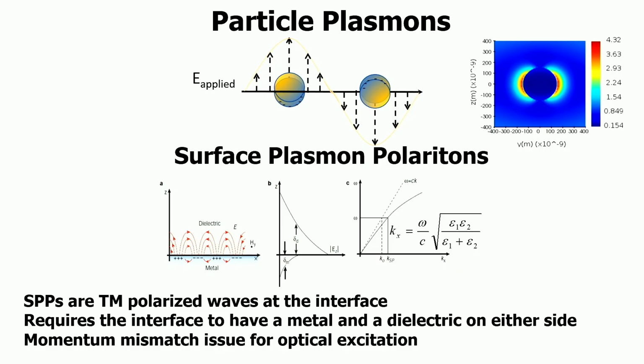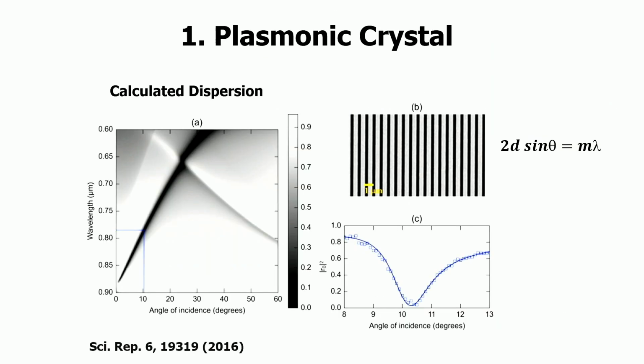To overcome this challenge, people started designing or structuring the metal or the dielectric. The simplest structure is a plasmonic crystal. You can take it as a one-dimensional grating. It can be a metal grating on top of a dielectric, or a thin continuous metal film with a dielectric grating on top. If you look at the calculated dispersion, there are two interesting features which we see.